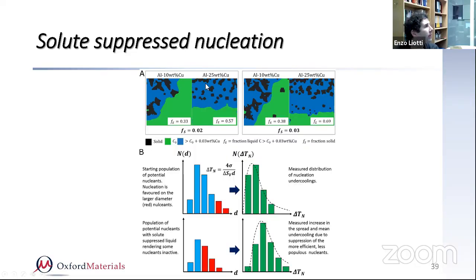If you create the blue area, it is a zone in which nucleation cannot take place because it has been suppressed by the presence of the solute that has been rejected by the solid crystal. If this area, compared to the overall undercooled area, is large, then when nucleation takes place, it will take place at higher undercooling. The schematic here shows that you are able to activate more grains when you solute suppress more, because you suppress the easy to nucleate grains that would otherwise kill the nucleation of higher undercooled seeds.